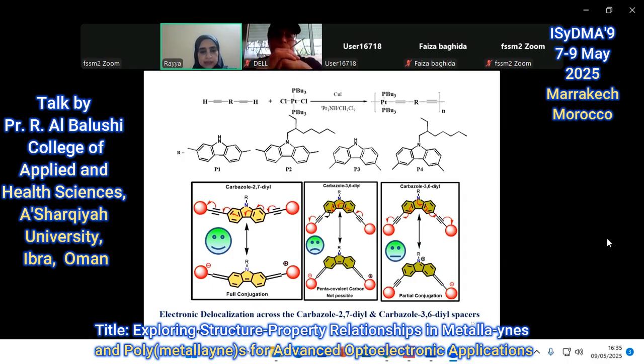So we started by synthesizing our materials, and we added our acetylide ligands through carbon 2 and carbon 7, which is a somewhat linear structure. We also compared this with the other ligands where the acetylides are connected through the 3-6 positions, and we found that by having more linear systems, the conjugation is more, as it is clear here. We have better conjugation in 2,7 compared to 3-6, where there is a hindrance in the conjugation. So we came to the conclusion that we need to work on this one in order to improve the properties so that they will be better than what is available in the market.